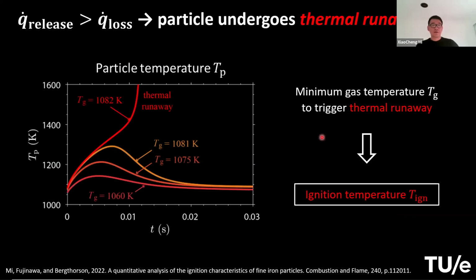And here are some sample results. On the left, what you are seeing is a whole bunch of curves. They represent particle temperature as a function of time for different gas temperatures. So what is ignition? Ignition is when the particle's heat release rate surpasses its heat loss rate. If this happens, we say that we trigger the particle's thermal runaway, right? If you change your gas temperature from a small value and gradually increase it beyond some critical value, you can trigger thermal runaway. And this minimum gas temperature that can trigger thermal runaway is determined as the ignition temperature. So by running the model multiple times with different gas temperatures, we can determine ignition temperature theoretically.